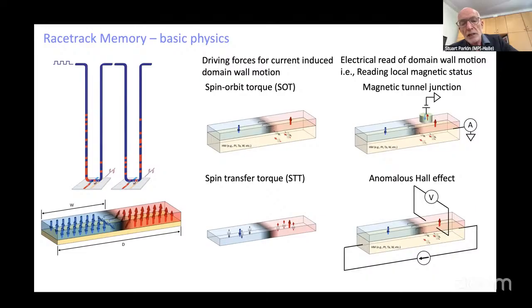These heavy metal layers display something called the spin Hall effect, which means that a charge current passing through a heavy metal layer will be subject to spin orbit effects, whereby electrons with spins up and spin down will be scattered differently to the left and to the right. And this means it looks like a Hall voltage, but it's completely spin polarized. And so on one surface you would generate spins pointing up, and on the opposite surface spins pointing down. And on one surface, the spin current you generate can diffuse into a neighboring magnetic layer and give rise to a torque through the spin angular momentum. So this is the concept.